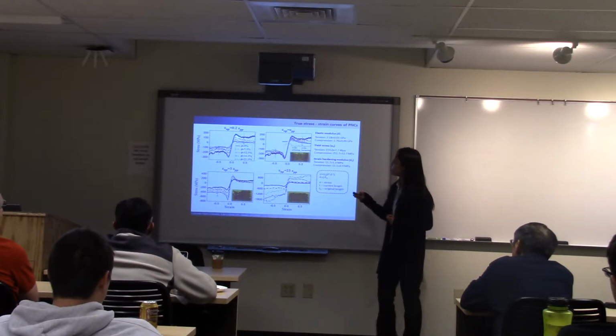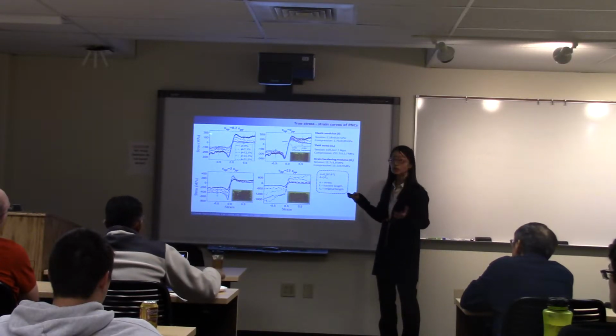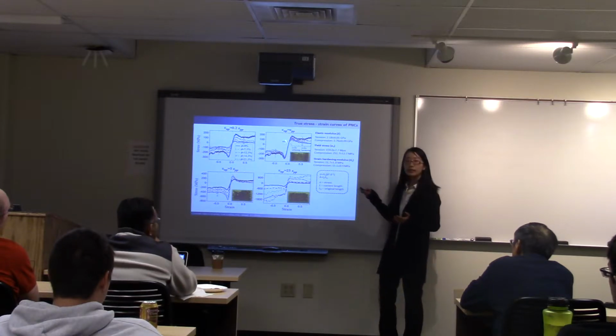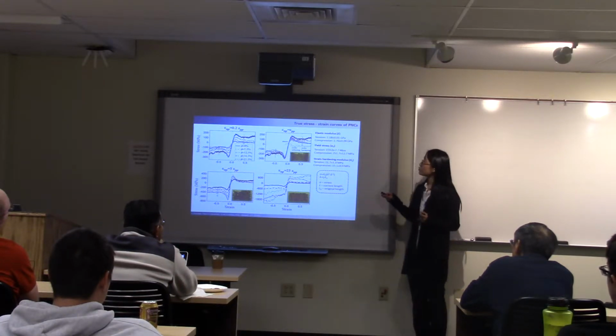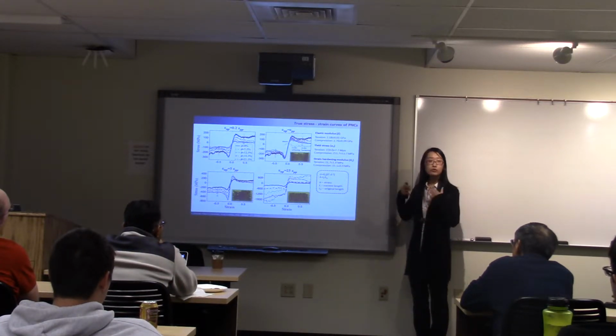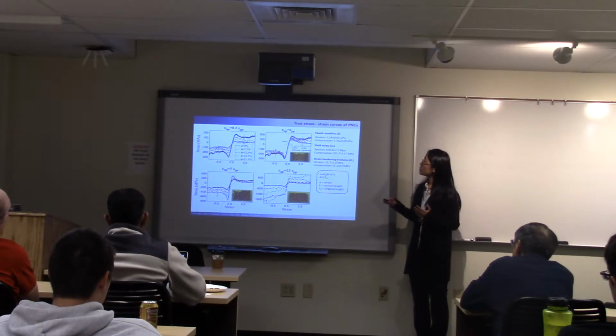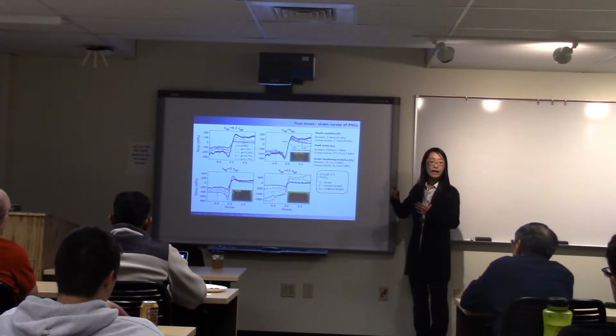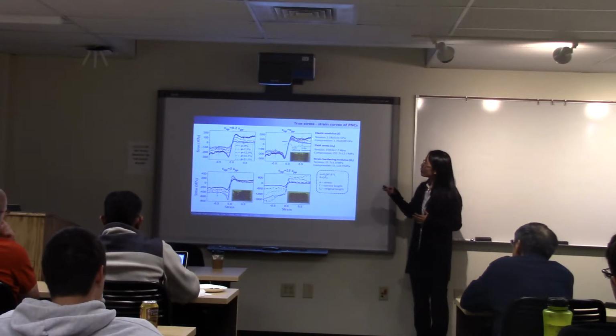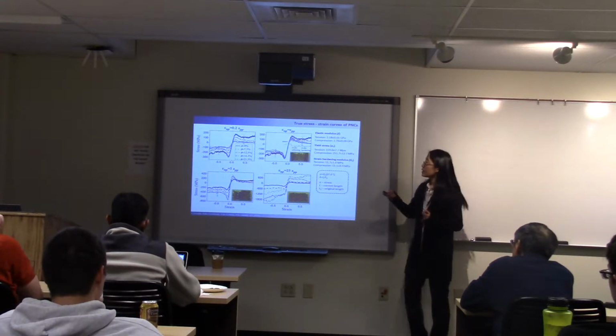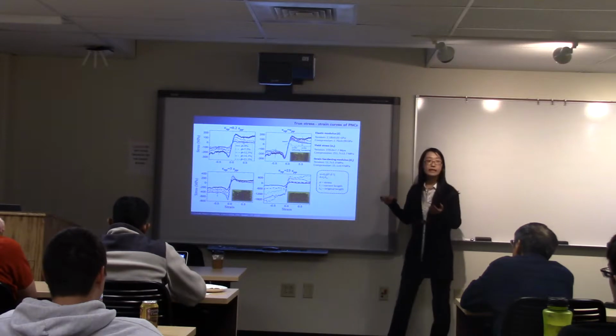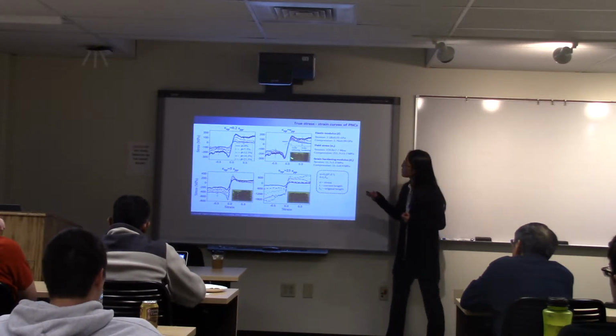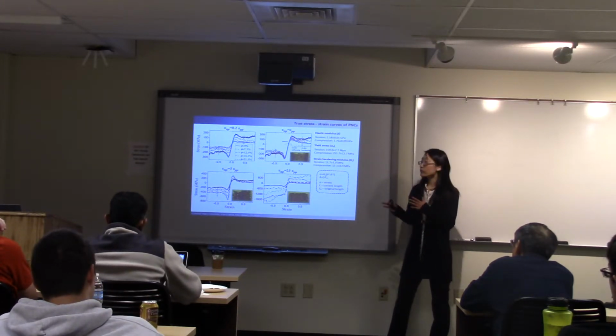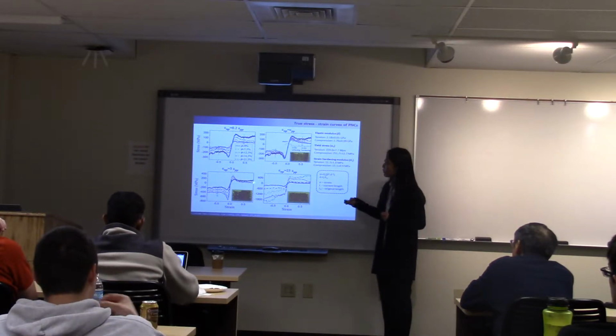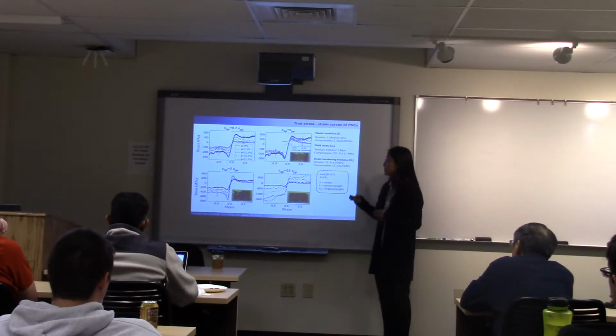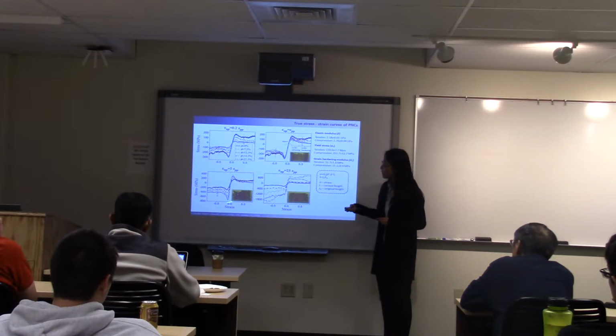So we find that when the nanoparticle-polymer interaction strength is smaller or equivalent to the polymer-polymer interaction strength, the NP addition is not reinforcing the polymer nanocomposites. We can see those lines are lying under this pure polymer line. Combining with the snapshots we saw on the previous slide, this is caused by the nanoparticle agglomeration that could weaken the material.